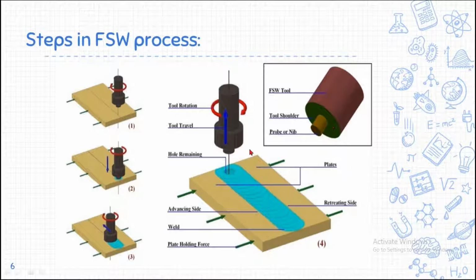So any variations in this tool, such as increasing or decreasing the tool pin diameter and tool shoulder diameter, greatly influence this process. For example, say this plate is around 5 to 6 millimeter. If you want to weld a plate of around 10 millimeter, you need a bigger tool compared to this one.